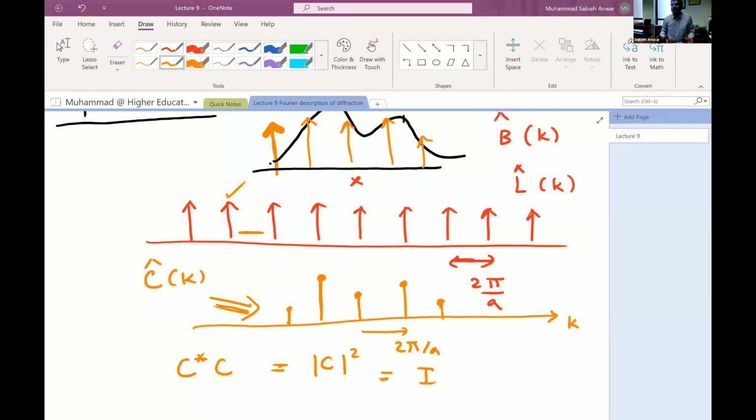Okay. Now in the next lecture, I will try to use this formula. I need to find out the Fourier transform of the basis, by the way. I can use simple arguments from wave mechanics to find out the Fourier transform of a collection of atoms, since the scattered X-rays are really coming out from the electron density. So I need to find out the Fourier transform of the electron densities of each motif, of each basis. And then I know that I need to sample them at the reciprocal lattice points, and that will give me the strength of the diffraction peaks. I already know what directions the diffraction peaks are coming out in.